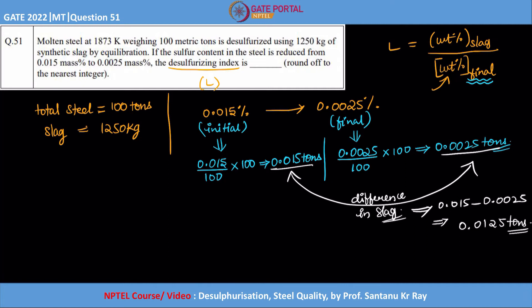Now we have all the weights so we can easily calculate the weight percentages. So from here L will be equal to weight percentage of sulfur, which is weight of sulfur divided by weight of slag. So this is nothing but the amount of sulfur that we have, 0.0125 divided by the weight of slag 1.25 tons. I can write this because everything is in tons. Let us try to convert this 1.25 into 100 divided by...